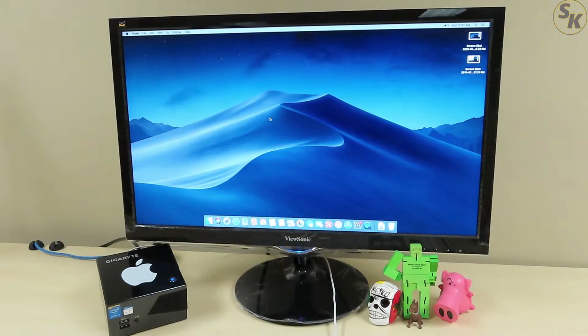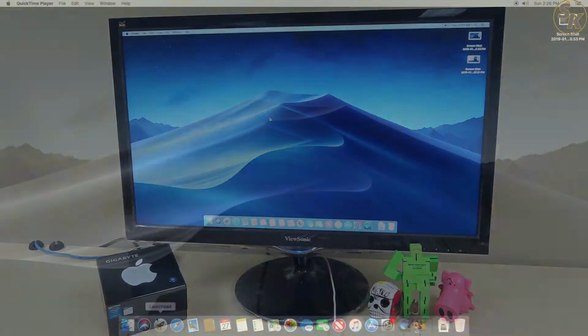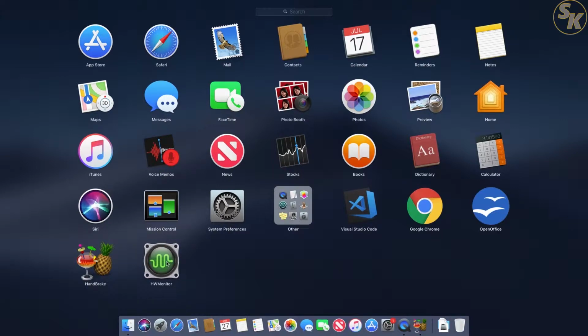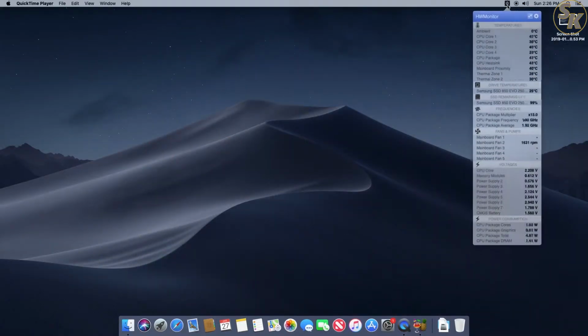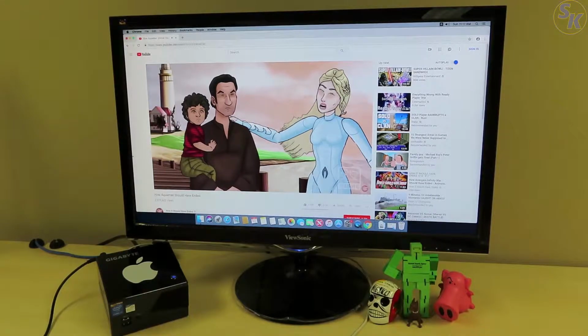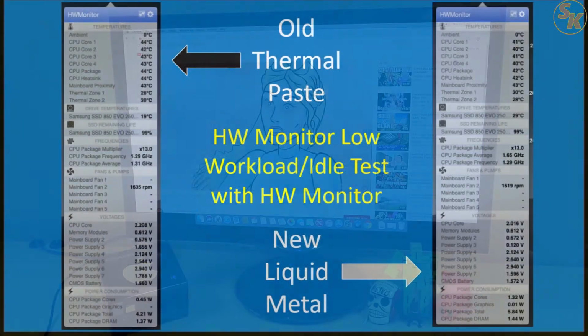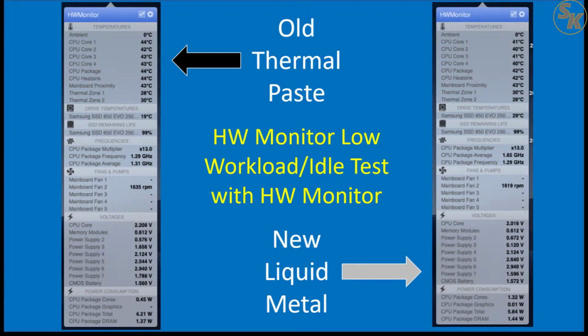I apologize for the lack of detail, but due to time constraints, I used the hardware monitor app that I installed in my last video to measure temperatures and RPMs during different points in time. For the first group of readings, I collected these when the PC was running for at least 10 minutes and running a low workload, like a browser window. Comparing both readings from when the PC had thermal paste and liquid metal, it's pretty much a wash. Both the fan speed and temperatures were in the same range, and sound was the same as well.